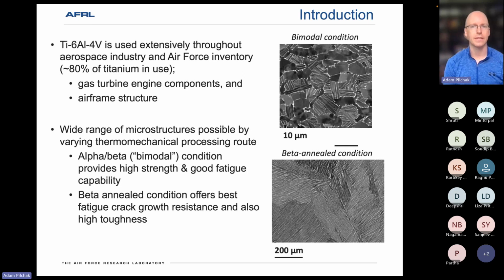Alpha phase is hexagonal close packed, and the beta phase is body centered cubic. The vast majority of the microstructure, 93%, something like that, is the alpha phase. So it definitely dominates the mechanical response. And that condition is known to be a really good balance of strength, ductility, and fatigue performance. But compared to the other microstructure below, the Beta-Annealed condition, bimodal does suffer a little bit in terms of damage tolerance, and specifically crack growth rate and toughness.